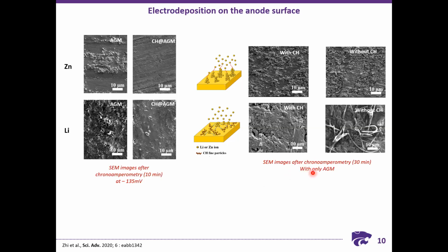So as you can see from here, they did a chronoamperometry for 30 minutes with only AGM without any interlayer, but with the CH added to the electrolyte. You can see that with CH and without CH. With CH in the electrolyte, there is indeed inhomogeneous deposition, but the severity of the big chunks of metal is lesser than when they didn't have CH in the electrolyte. Similar in the case of lithium. So with the CH present in the electrolyte, there is an improvement in the electrodeposition of metals. However, it could not prevent the formation of mossy lithium or dendritic lithium. So it is quite necessary to have an interlayer to regulate the flow of ions to have a homogeneous deposition.